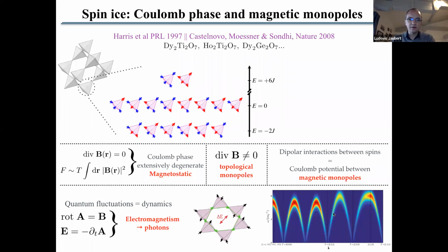This paper is from Benton and collaborators from 2012, if I remember correctly. This is energy omega as a function of wave vector k, and this linear dispersion here is the band structure that you can get from quantum spin ice, and it corresponds to these photon excitations because omega equals k times c. So this slope is directly related to the effective speed of light that you get in quantum spin ice.